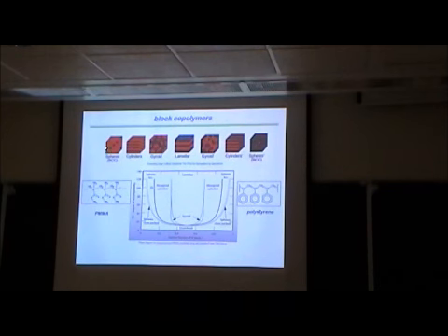In this case, polystyrene is the minority phase. You end up with little polystyrene balls in a matrix of PMMA. Then cylinders, and then roughly equal volumes create a lamellar phase. Again, this is flexible, this is more rigid. So if we were to take this molecule and cut it in half, then these two solutions in a melt would just phase separate. So the molecular connection forces them to make these nanoscale structures characterized by this interface.